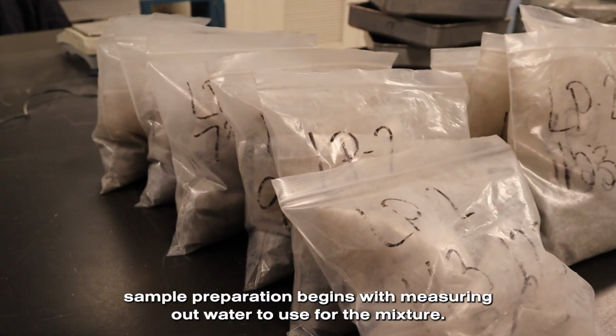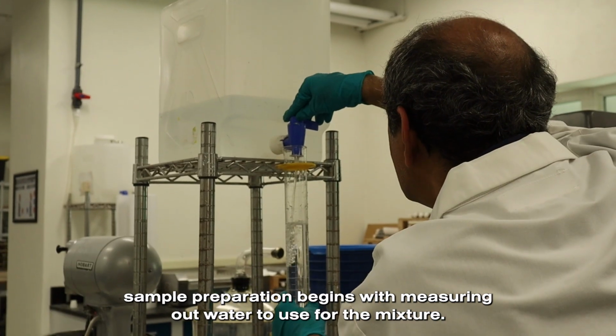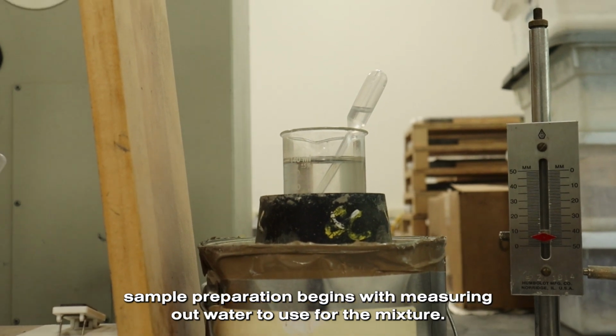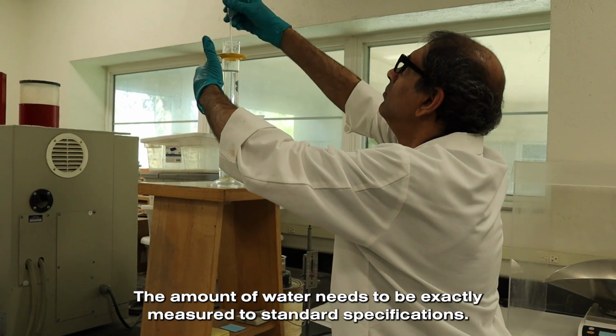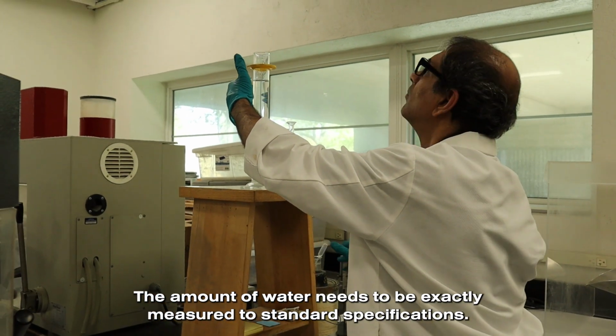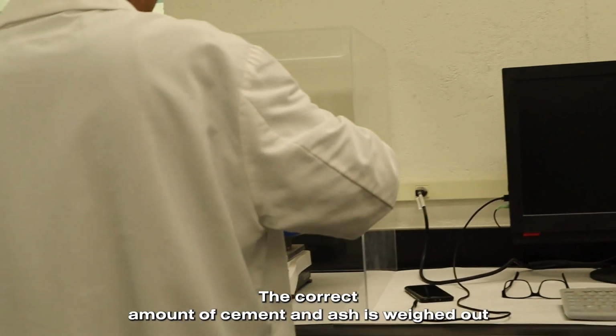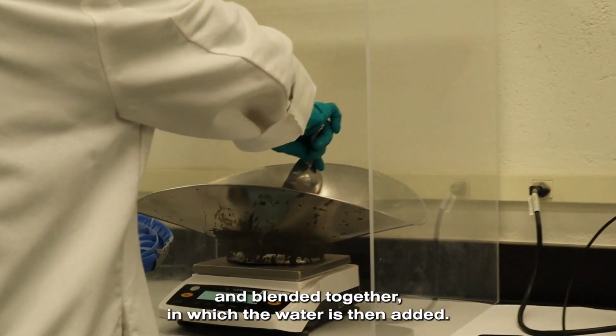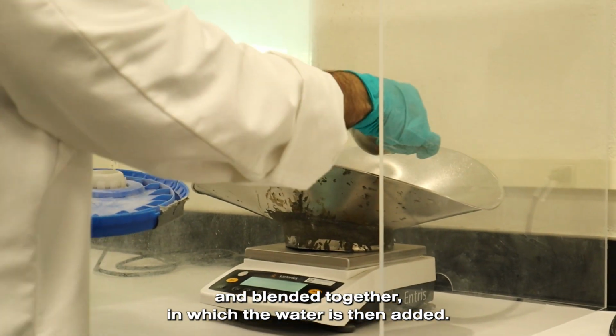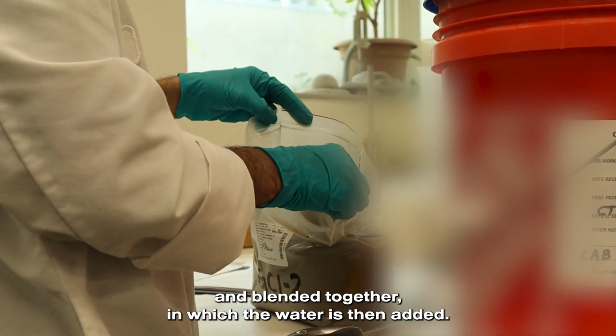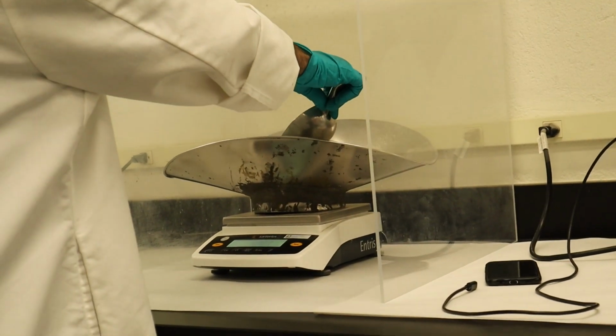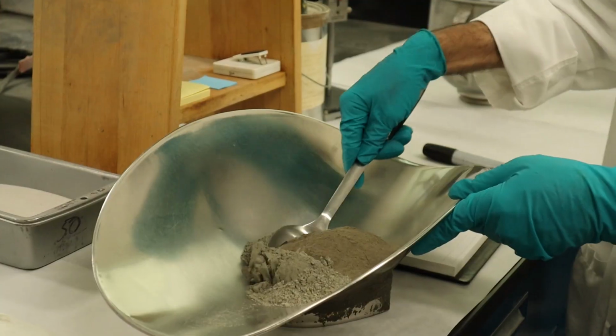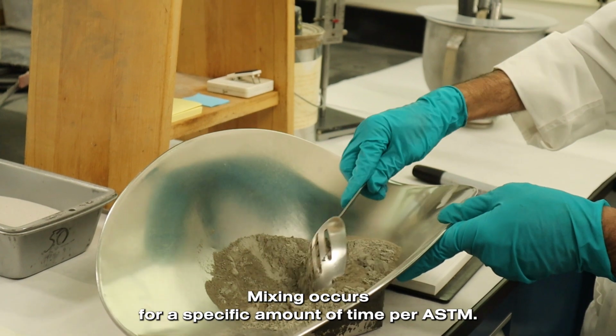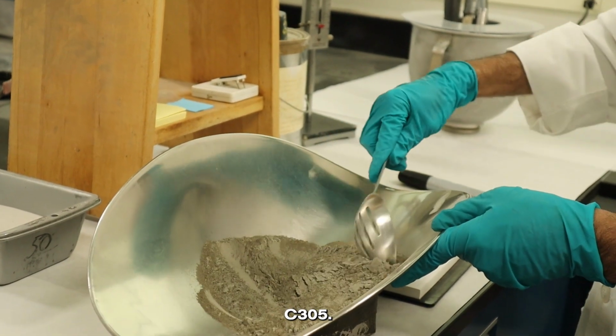In our mortar lab, sample preparation begins with measuring out water to use for the mixture. The amount of water needs to be exactly measured to standard specifications. The correct amount of cement and ash is weighed out and blended together, in which the water is then added. Mixing occurs for a specific amount of time per ASTM C305.